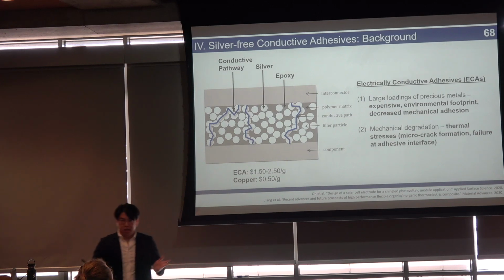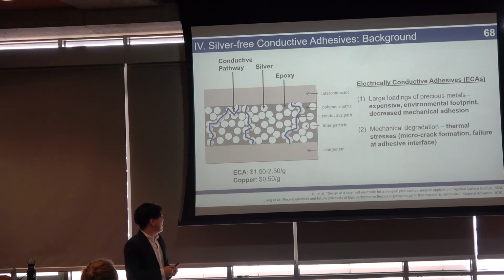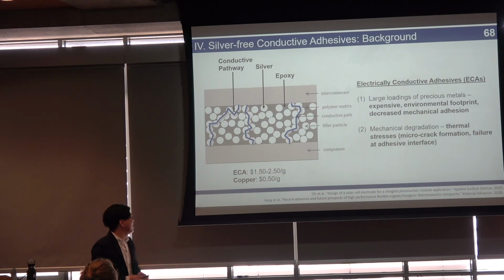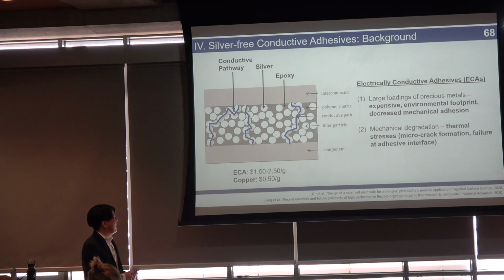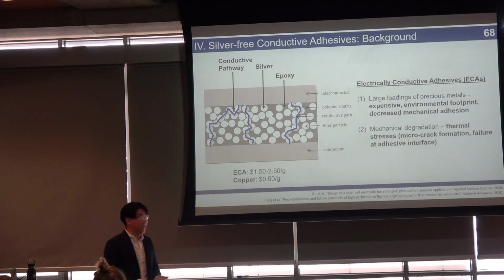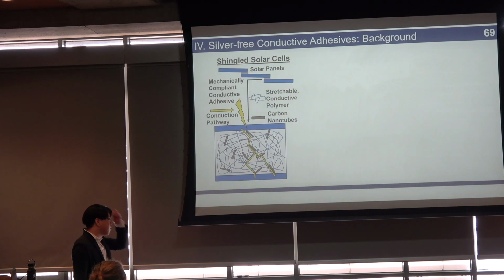But under the ruthless fist of capitalism, all we really care about is the actual cost. For commercial conductive adhesives, you're looking at a price of about $2 per gram, but copper is about a fourth of the price of that. So even though you have to factor in a more expensive manufacture process that involves heating your material, it still ends up being cheaper than your conductive adhesive.